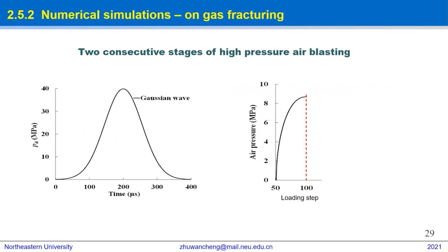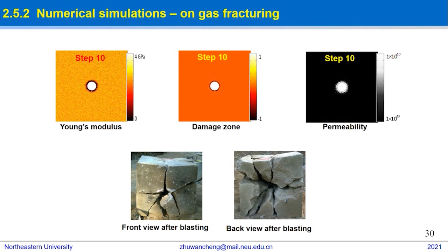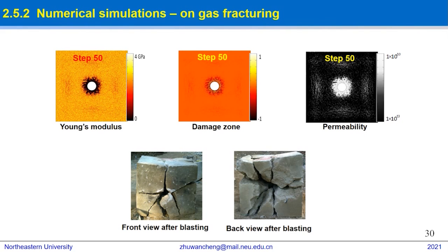This slide shows the 2 consecutive stages of high-pressure air blasting. In the first stage, Gaussian wave with peak pressure of 40 MPa, and duration of 400 microseconds are input into an elastodynamic finite element model for back analysis. Then air pressure applied at the quasi-static loading stage for high-pressure air blasting in the numerical simulation. It is seen from the damage zone or Young's modulus distribution at step 100 that the high-pressure air blasting induced cracks distribution compares well with the experimental observation.